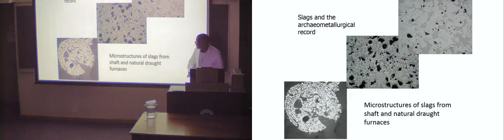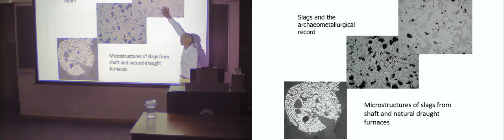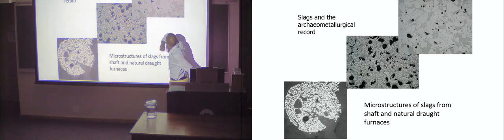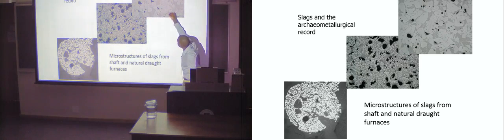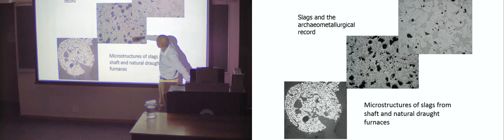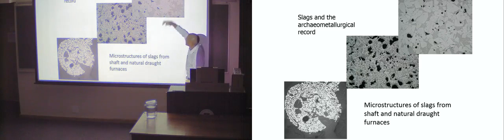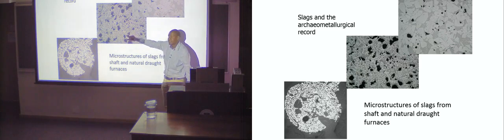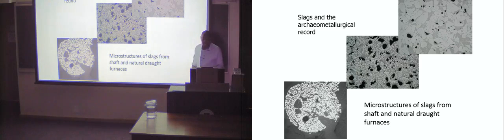So this is perhaps a much clearer image, and this is all blocky ferrite. And as you can see, there is less in terms of these lighter phases, which means that perhaps on the basis of this, the furnace that produced this slag was more reducing than this one. So that's an example of how we would build arguments about the efficiency of reduction.